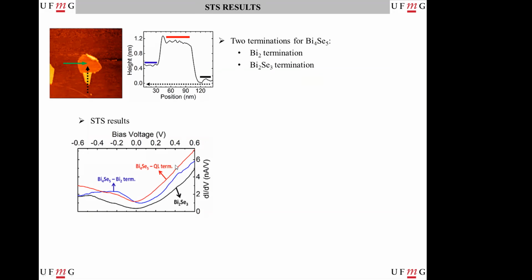And we have the other two structures here. The bismuth four selenium five, with termination of a quintuple layers, is pretty much similar to bismuth two selenium three, but with a little bit of the metallic character of this structure increased in relation to the two-three sample. And we have this one that's pretty much different from the other ones, with the bilayer termination here.